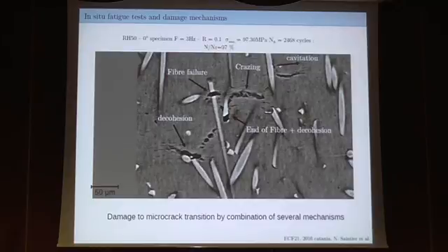This is a typical picture that we obtained. Here you have something which is more or less a crack here. So what do we have here? We have decohesion between the matrix and the fiber. We have cavitation here between those two cavities. You have fiber failure at the end of the fiber plus decohesion. You have crazing, and you have cavitation next to the interface that initiates a crack here, a micro crack. So the final micro crack is really obtained by the combination of several mechanisms.